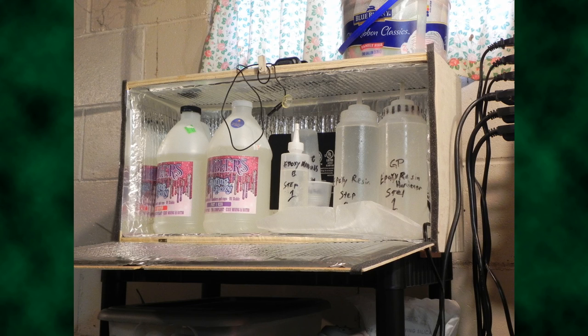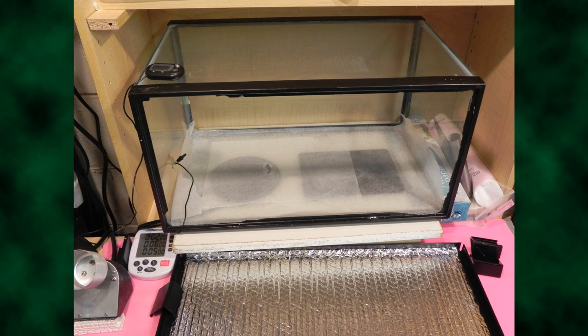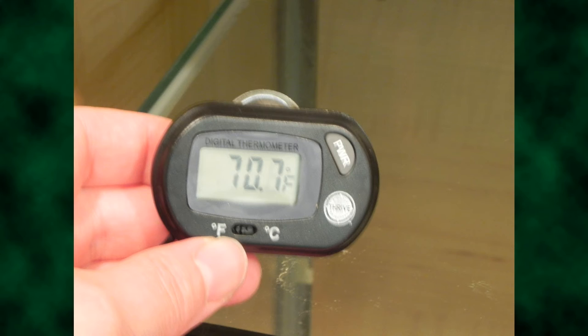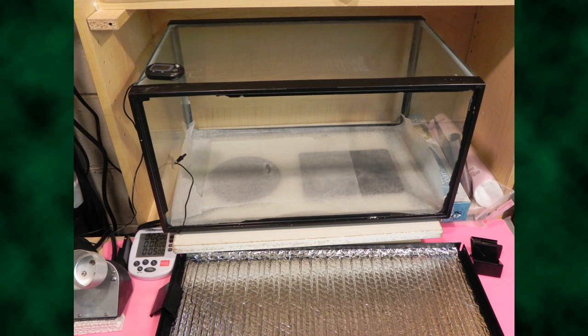The curing temp is also critical. Too cool and it will be too rubbery and sticky. Too warm and it can flash cure with lots of bubbles. To prevent this, you can create a hot box. This is a small chamber that is heated. In my case, a 10-gallon tank with reptile pad heaters and a temp gauge. Using this, I can keep the curing resin in the 70-degree range that is ideal, as well as protect it from dust. This is helpful in areas where temperatures fluctuate out of the curing range.